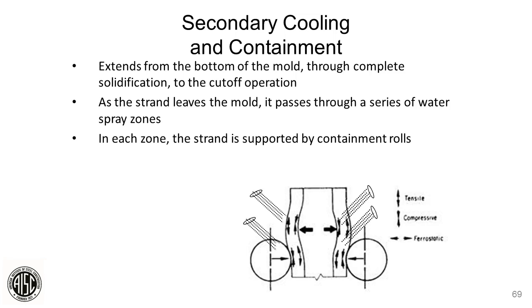It extends from the bottom of the mold, and we have these rolls that keep compressive force on the steel, so we don't have any bulging. If the ferrostatic pressure exceeds the strength of the shell, the liquid steel can actually penetrate out, and we call that a breakout, and that's a casting terminating event. We don't want that to happen. And next slide, please.